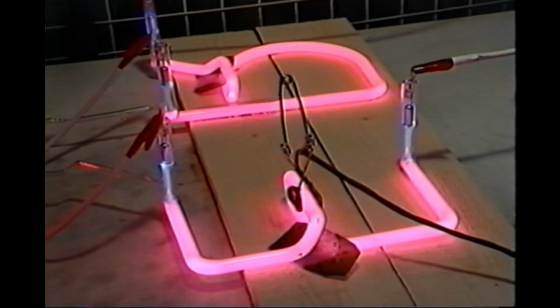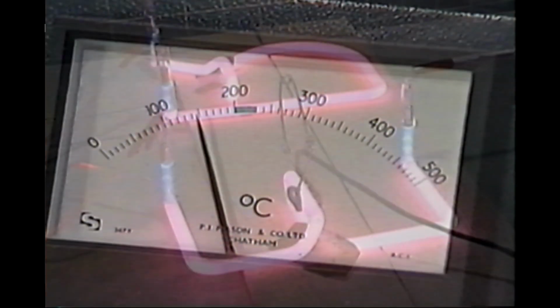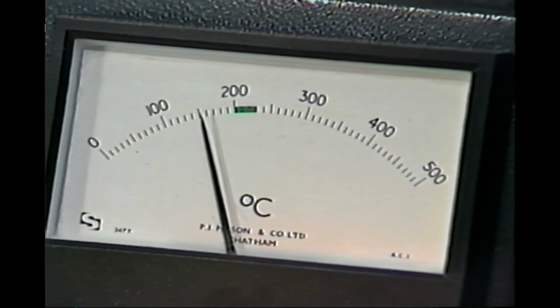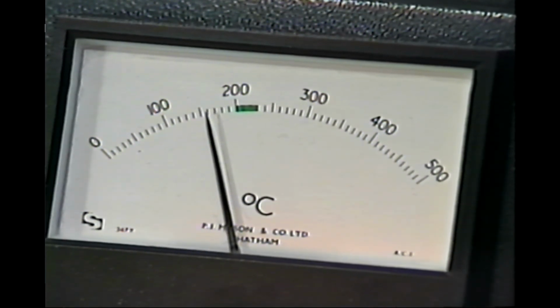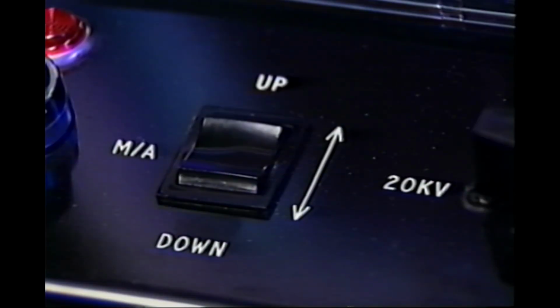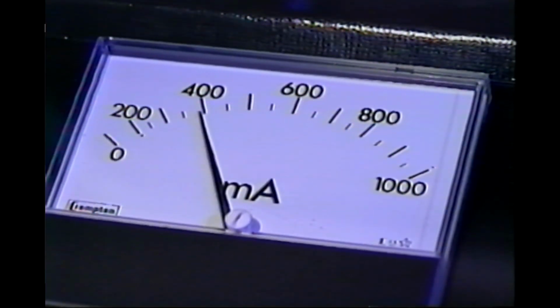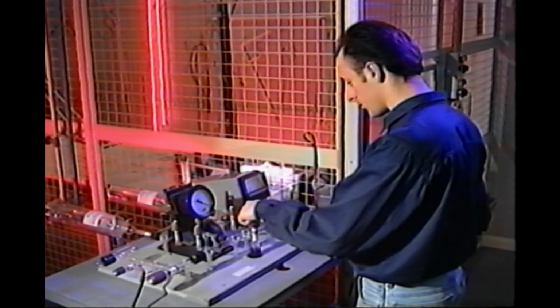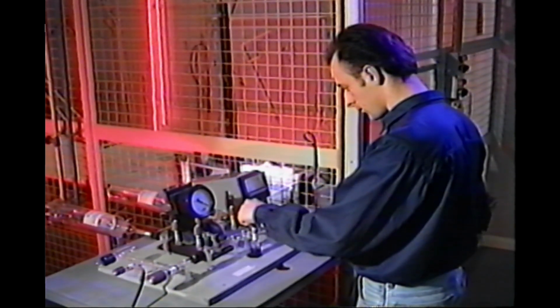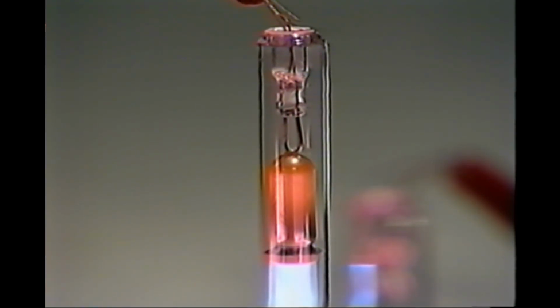Allow the bombardment to continue, increasing the current slightly if necessary to effect gradual heating of the tubes until the temperature reaches between 150 and 170 degrees centigrade. At this point, increase the current to 400 milliamps. Open fully the main stopcock. Allow bombardment to continue until all the electrode shells are glowing bright orange-red along their whole length, an approximate shell temperature of 900 degrees centigrade.